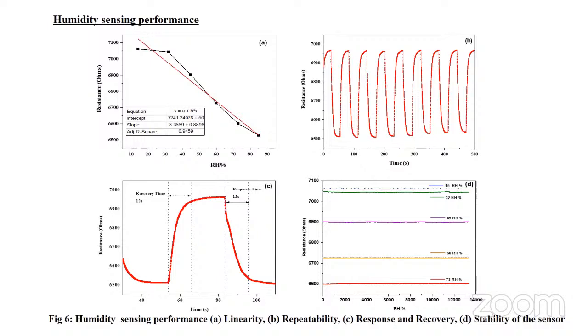The stability of the sensor was tested for several hours at different humidity levels. The resistance was almost unchanged through the testing period, proving excellent stability and durability of the sensor. These results show a good compatibility of the fabricated sensor for high performance practical applications.